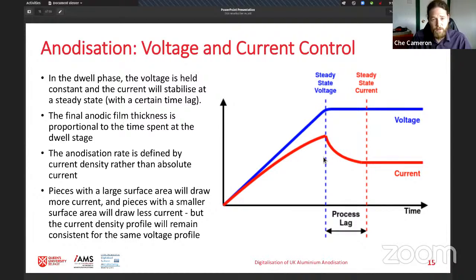An interesting note about this is that it has a sort of self-regulation built into it. So the rate of the anodization is based on current density, or current per area of workpiece, not the absolute amount of current that is going into the job. And that just means pieces that have a large surface area will draw more current, pieces with a small surface area will draw less current, and that's generally why we'd use a voltage control for anodization processes.